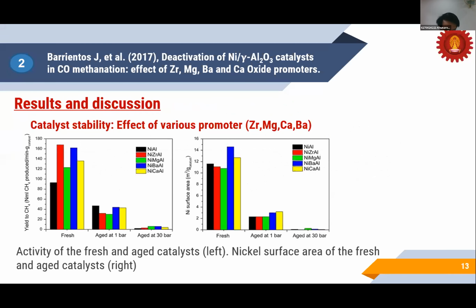As can be seen, all the catalysts deactivate after the aging treatment. Indeed, the loss of activity is almost complete after aging at 30 bar. Moreover, as can be deduced from the figure, the loss of activity is explained by a loss of nickel surface area. It may be noted that under this operating condition, all the promoters present a positive effect on the initial catalyst activity.